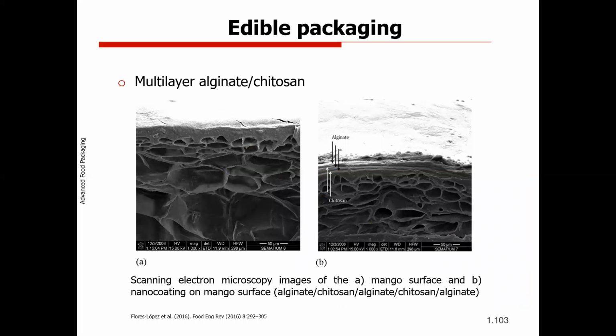I want to show this detail. We also did this on a mango surface, in this case with alginate and chitosan, and then we cut the mango and did the cross section analysis in the scanning electron microscopy, and we saw this. This image A is the mango surface, which is dried, and then here you have the different multi-layers and coating that is formed by this multi-layer system. You have the chitosan and alginate, in this case 5 layers. So with this image and other techniques, we show that we are building this multi-layer system on the surface of the fruits.